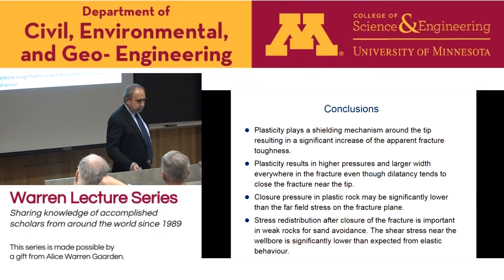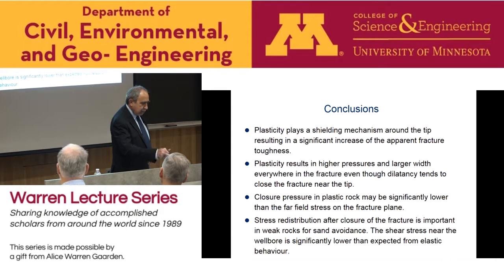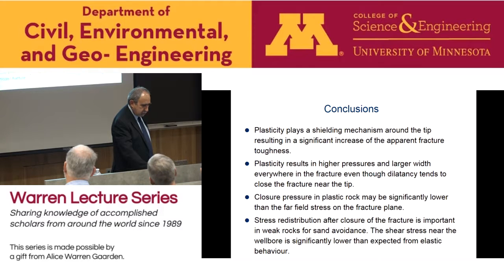And I reached the conclusion, just quickly to say, plasticity plays a shielding mechanism around the tip, resulting in a significant increase of the apparent or effective fracture toughness, as we call it, which results in higher pressure and larger width everywhere. Even dilatancy tends to close the fracture tip. Closure pressure in plastic rock may be significantly lower than the far-field stress on the fracture plane, and this will underestimate the closure stress in the calibration, which I said before. We have stress redistribution and more stable formation after fracturing.